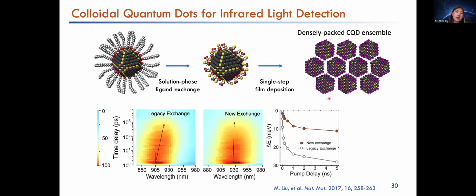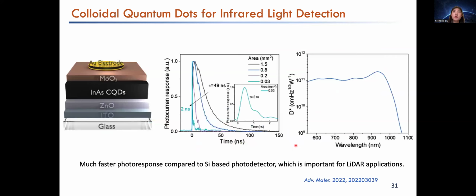So we recently developed some strategies that can improve the conductivity of the material by using a method called solution phase ligand exchange. This method can completely remove the insulating molecules kept on the surface of the quantum dot and replace them with very short ligands. Compared to the old exchange method, this new method can significantly reduce the disorder generated in the quantum dot film. And this method has been utilized on a lot of different types of quantum dots.